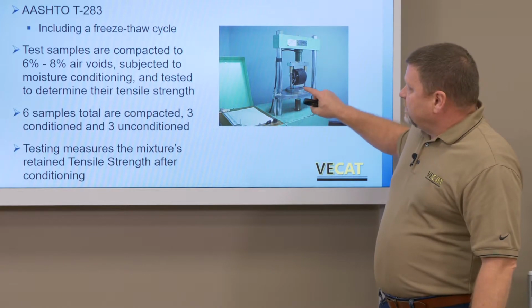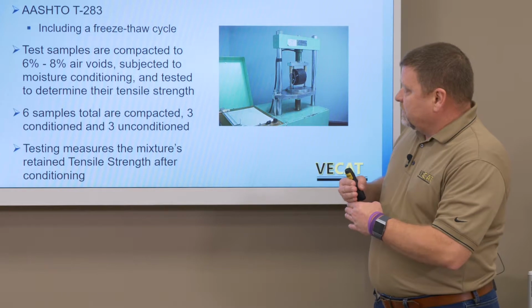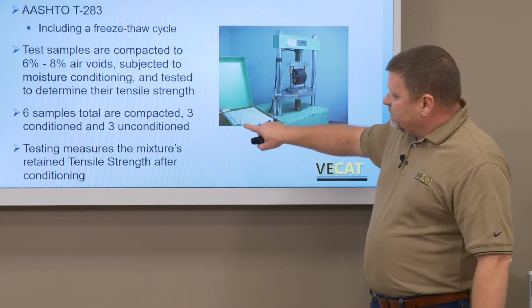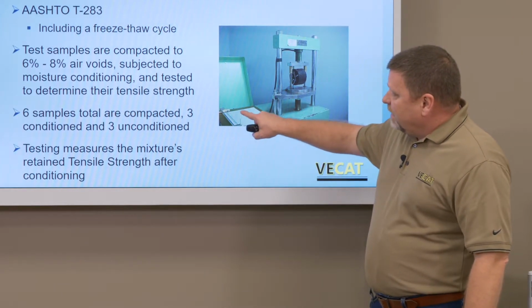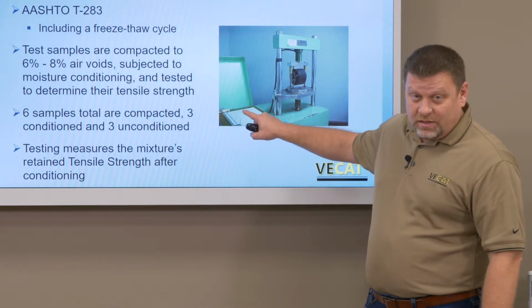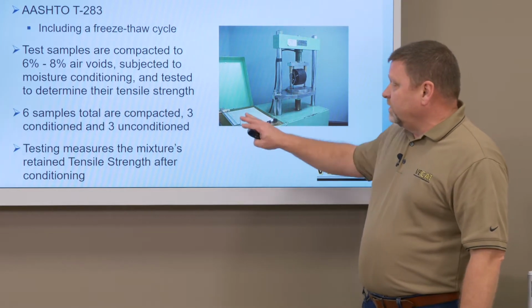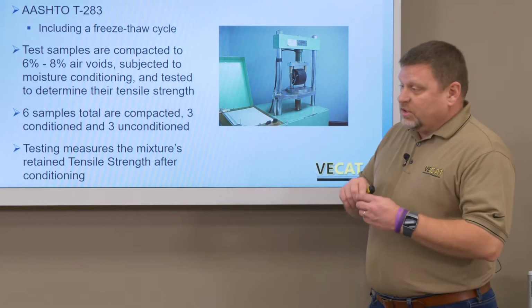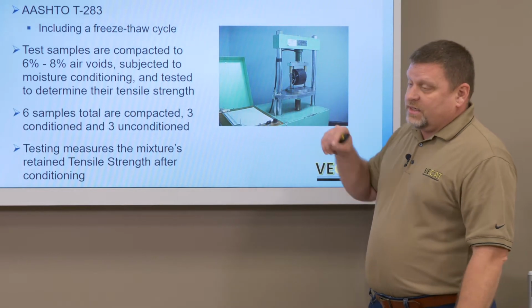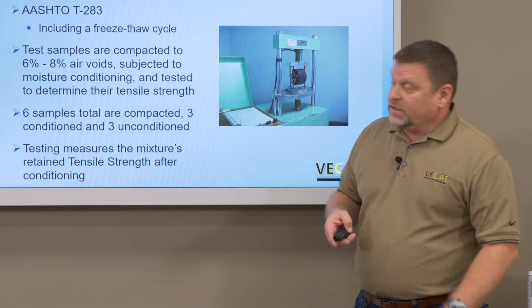So what happens is the specimen itself will crack right in half once the test starts. This piece of paper here will create a plot. I don't need the whole plot. All I need to know is the peak strength for this plot. Okay? Some newer pieces of equipment don't even have a graph like this. They just give you a number at the end of the test and it tells you the peak strength. That's the only number you need to do a calculation for TSRs.